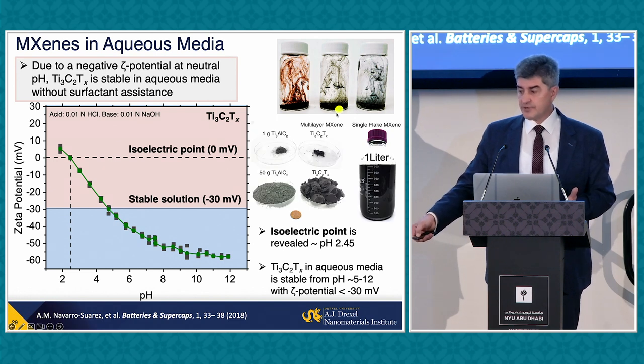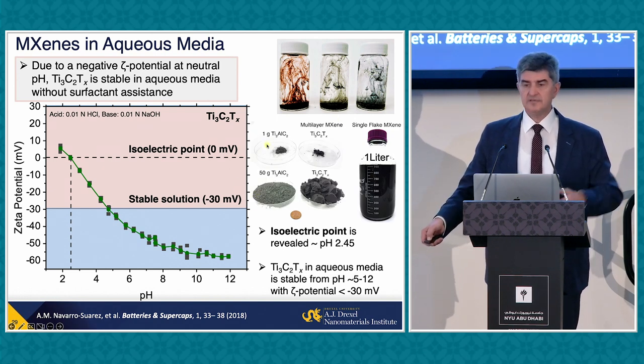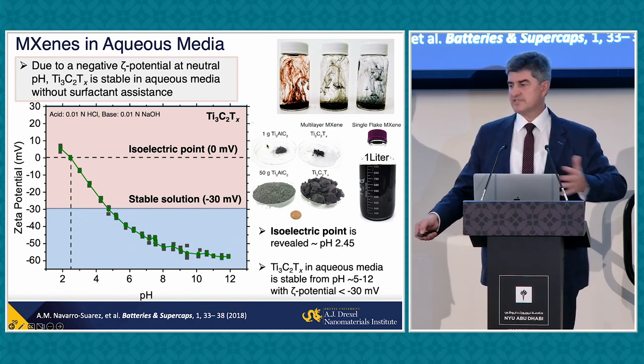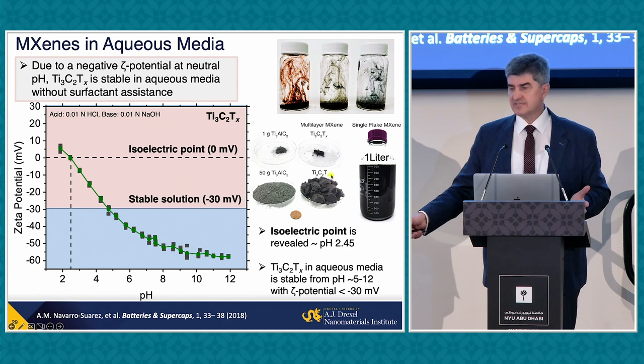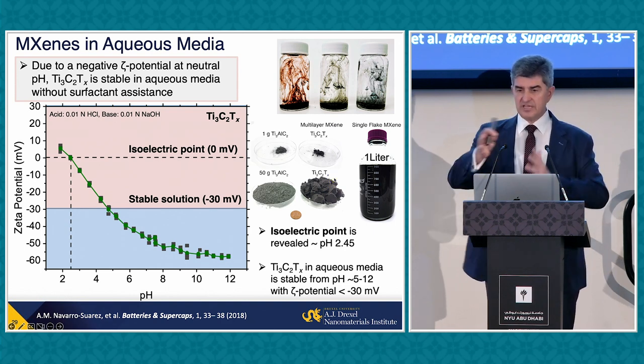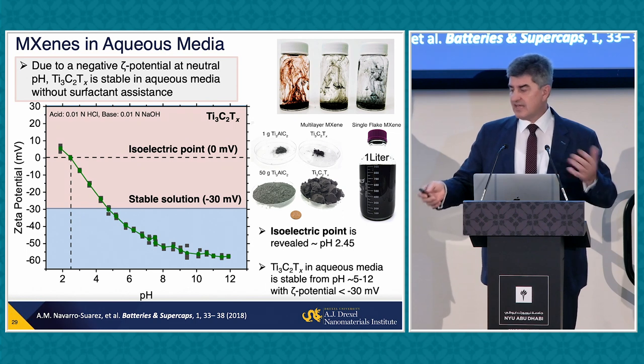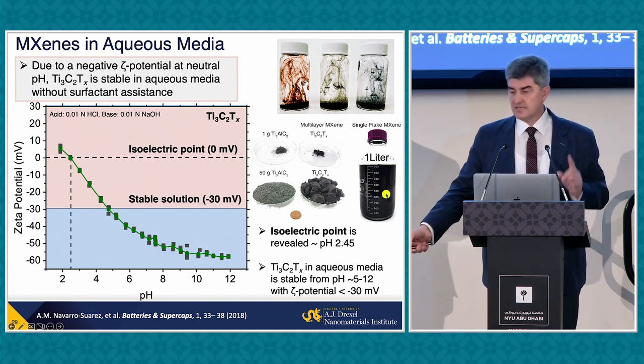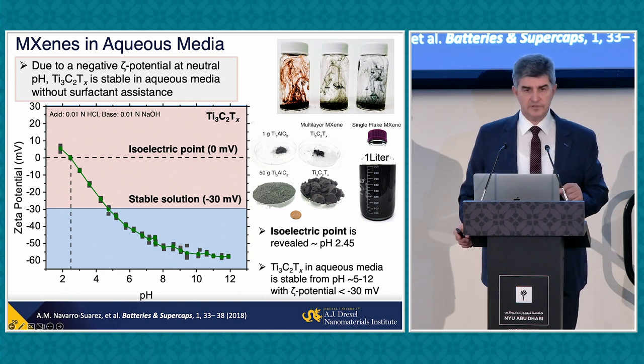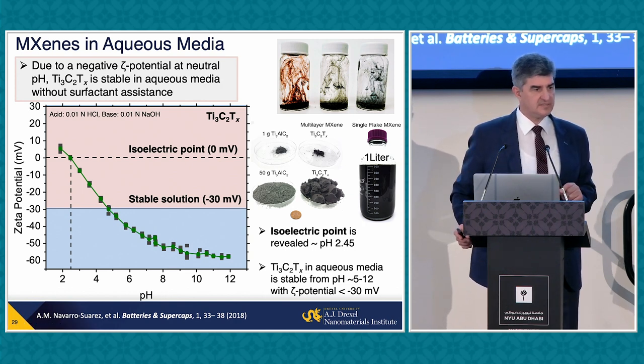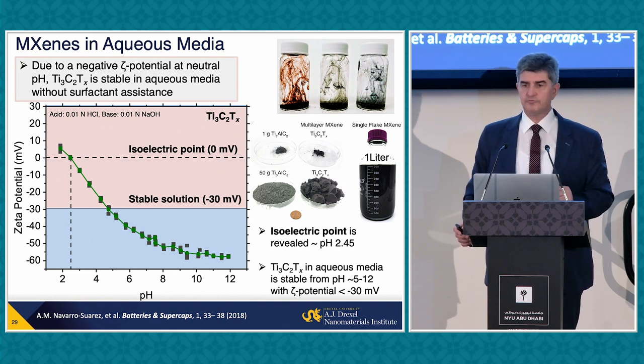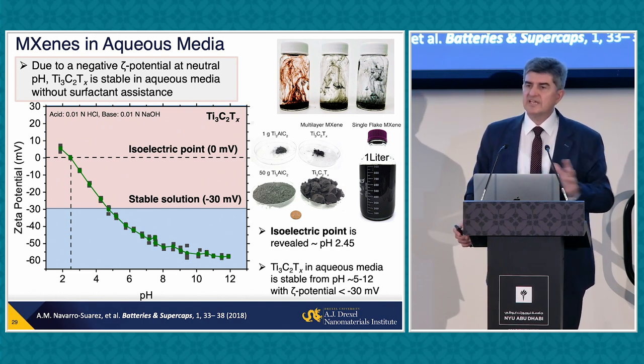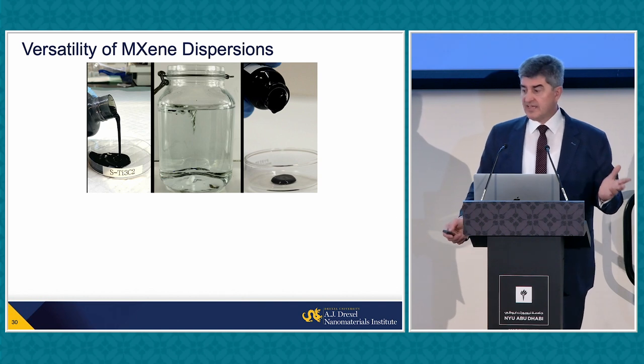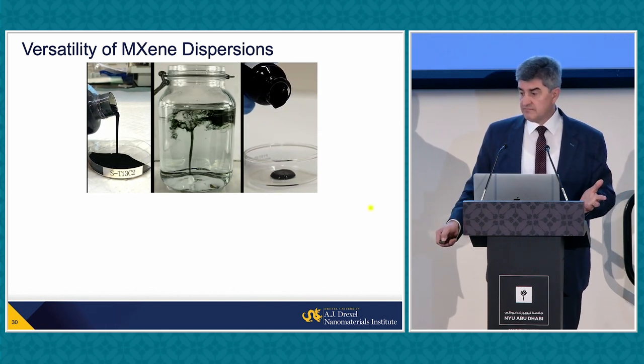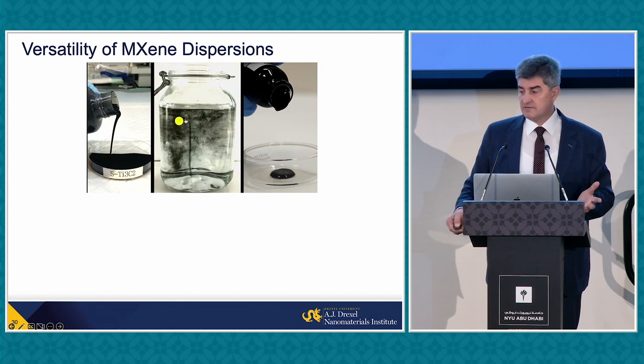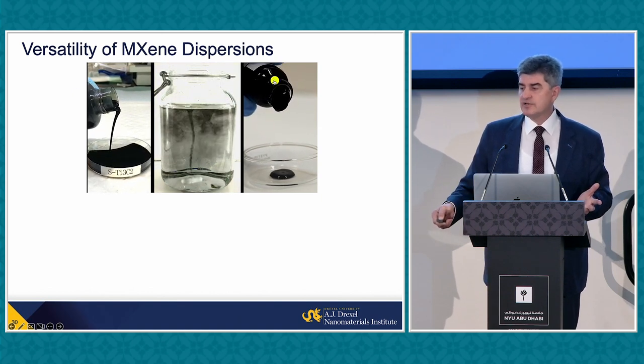So basically we take ceramic powder, we dump it into a reactor with a solution of etchant or molten salt. We make this multilayer material similar to clay, which can be sheared very easily, separated, and then we make a colloidal solution of flakes. What is very important, if you want to dissolve graphene in water or metal nanoparticles that have conductivity, you have to use surfactants that will not form colloidal solutions. Here, you don't have any additive, you don't have to burn it afterwards. Depending on concentration, you can make it dilute, for example, for inkjet printing, or you can make a very thick solution like honey.